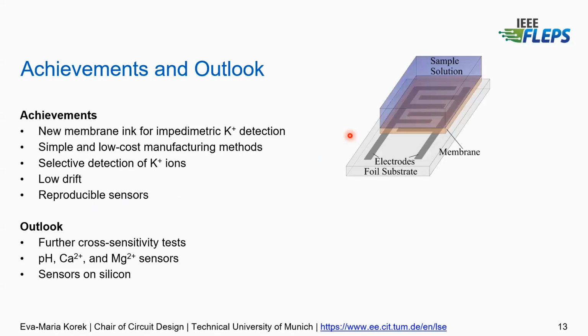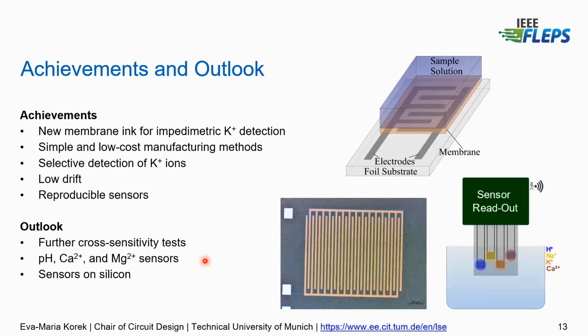And summarized, we can say that here we introduced a new membrane ink for impedimetric potassium detection. We introduced 2 simple and low-cost manufacturing methods, and the shown sensors showed a selective detection of potassium ions, low drift, and good reproducibility. And in the future, we want to conduct more cross-sensitivity tests. We want to make more sensors that can also detect pH, calcium, or magnesium. And we also want to bring the sensors on silicon. So here are our silicon electrodes, and we want to inkjet print the ion selective membrane on top of those.